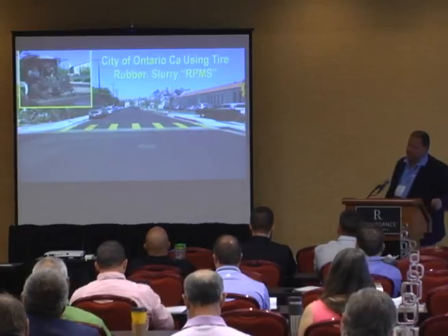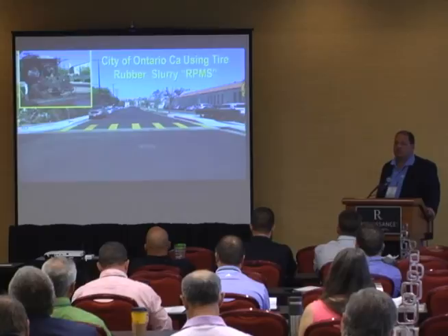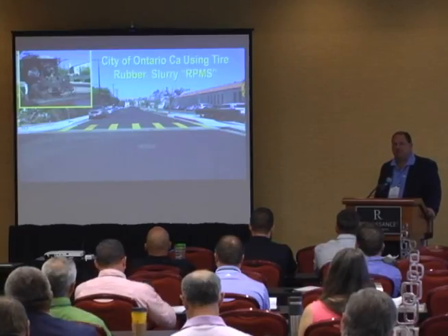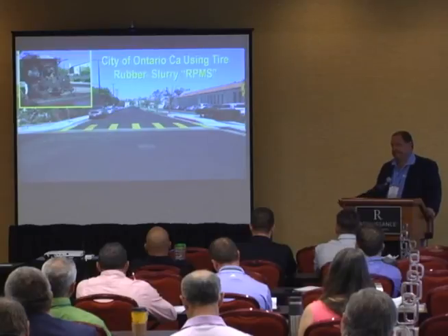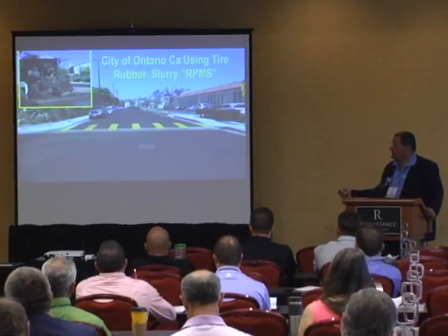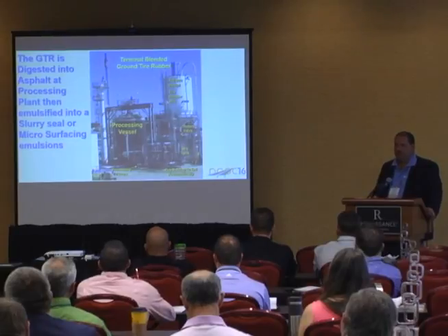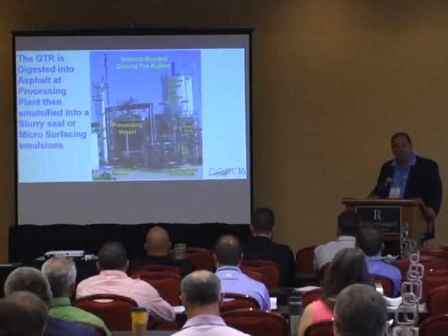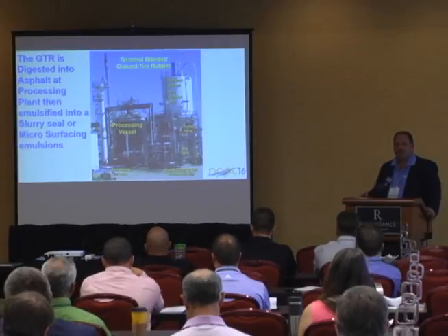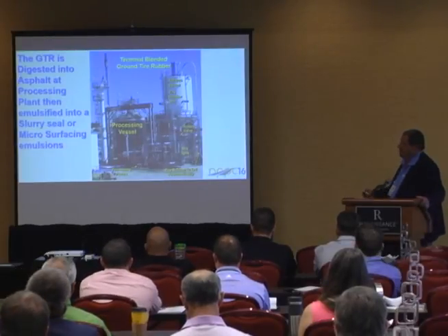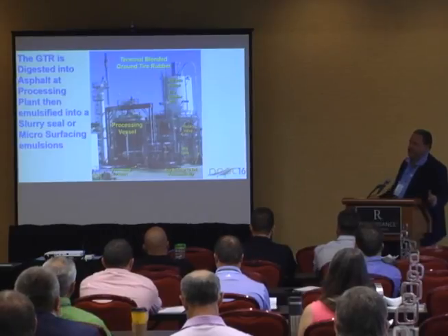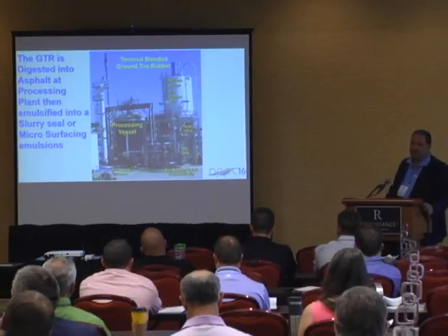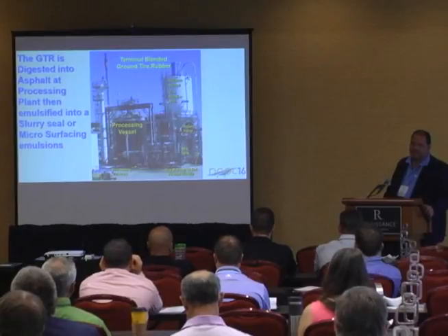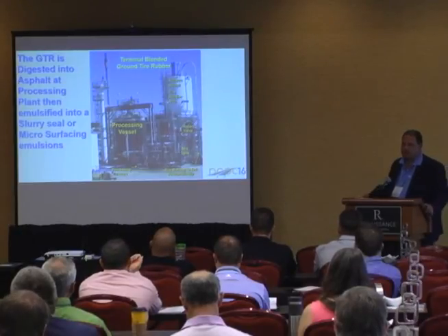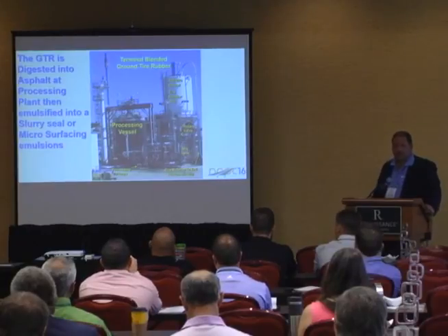City of Ontario has been running a program for the better part of 10 years, maybe almost 14 years, and they like it. They also have a requirement of carbon black, so it looks very black. Here's the terminal blend process, done at the refinery or at an asphalt terminal, where they take the ground tire rubber, melt it, put some high heat to it, and basically carbonize it into the asphalt, so you can get a weight certificate, get it in the asphalt, and put it down. That's a process that's done a lot in Texas, and a little bit in California.